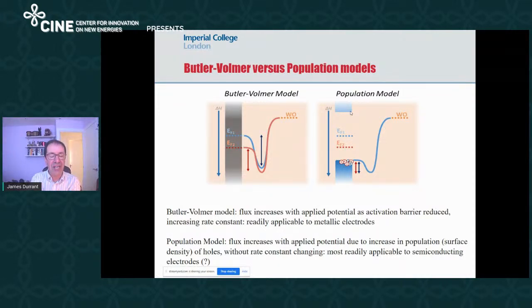Almost all electrochemical kinetics are analysed according to a Butler-Volmer model. The Butler-Volmer model essentially is a model developed for metals, which says as you apply a greater potential, then you lower the activation barrier to the transition state. And so the rate constant for the reaction goes up. And so as you apply a potential, the rate constant gets bigger, and so the reaction gets faster. This was a model developed primarily to describe electrochemistry on metal surfaces.